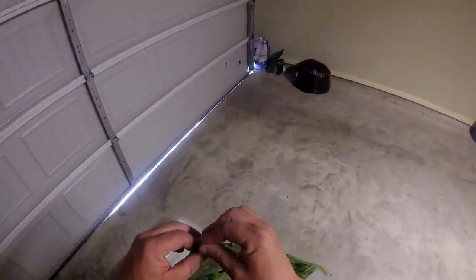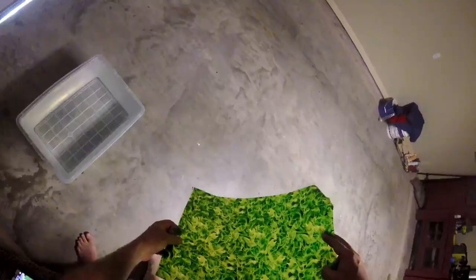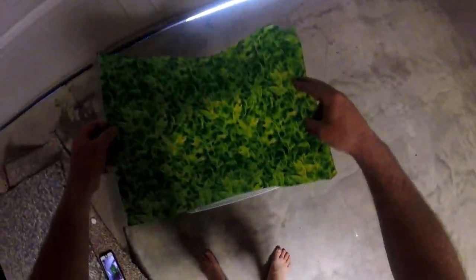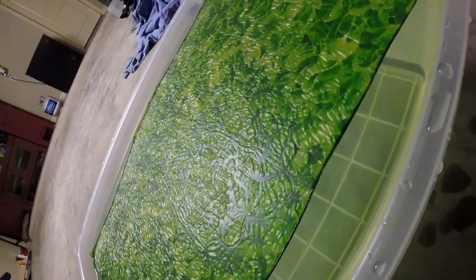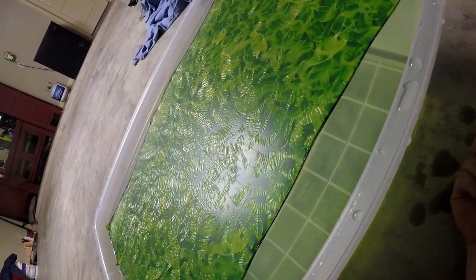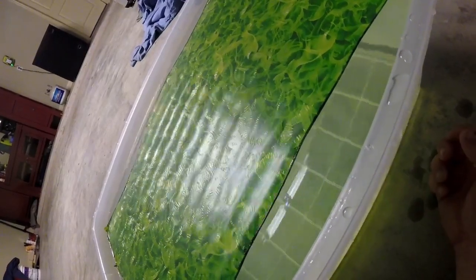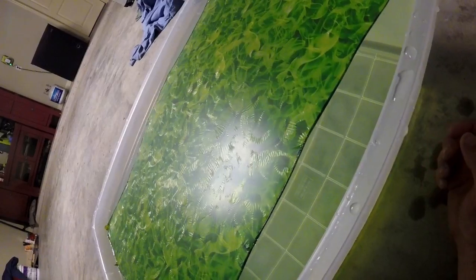One other thing: wet your fingers and test to see which side of the film is sticky. Then you lay it in the water sticky-side down and look for air bubbles. You'll see it's starting to expand — it'll get wrinkly and then start to square away. That's just it absorbing the water. Once you see it get smooth, you know you're ready to go.